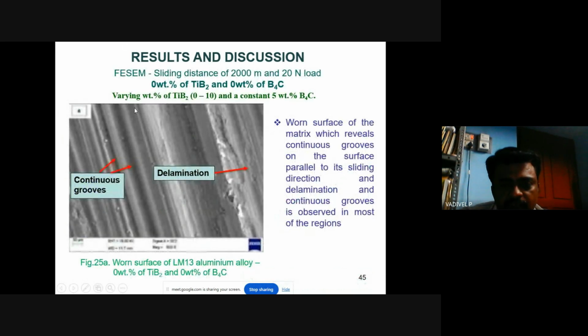In this study, zero weight percentage of TiB2 and zero weight percentage of boron carbide, that is only LM13 aluminum alloy, was used, and the wear test is done on the pure LM13 aluminum alloy. Here you can see the continuous grooves and delamination of this LM13 aluminum alloy. The surface of this matrix gives continuous grooves, one next to the other, parallel to the sliding direction. Delamination and continuous grooves are observed in regions.